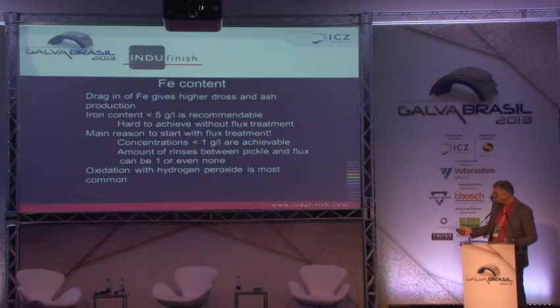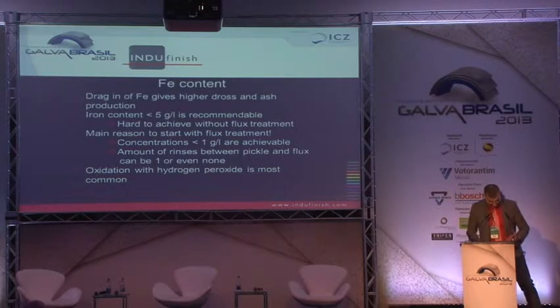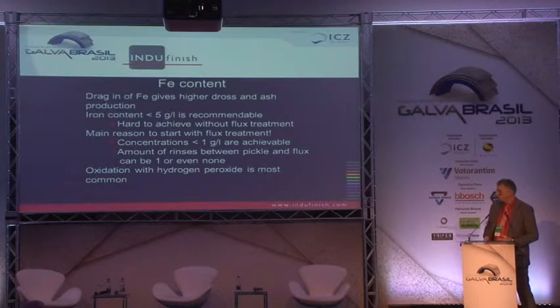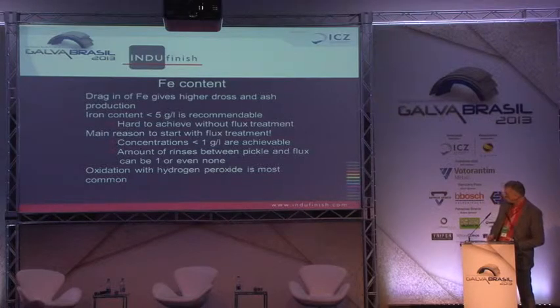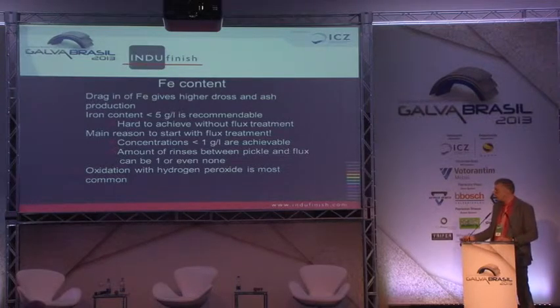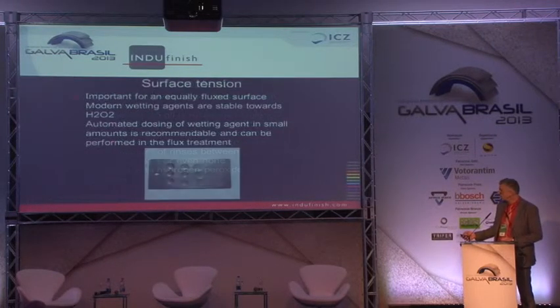Iron content, I've already talked about it. We think it's recommendable that you operate below 5 grams a liter. Most units that we installed are operating these flux tanks at about 1 gram a liter. And oxidation with hydrogen peroxide is most common. You can use other chemicals, but we are using hydrogen peroxide.